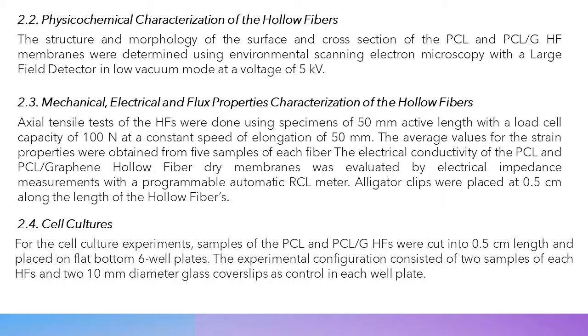Mechanical, electrical, and flux properties characterization of the hollow fibers. Axial tensile tests of hollow fibers were done using specimens of 50 mm active length with a load cell of capacity of 100 Newton at a constant speed of elongation of 50 mm. The average values of strain properties were obtained from 5 samples of each fiber. The electrical conductivity of the PCL and PCL graphene hollow fiber dry membranes was evaluated by electrical impedance measurements with a programmable automatic RCL meter. Alligator clips were placed at 0.5 cm along the length of the hollow fibers.